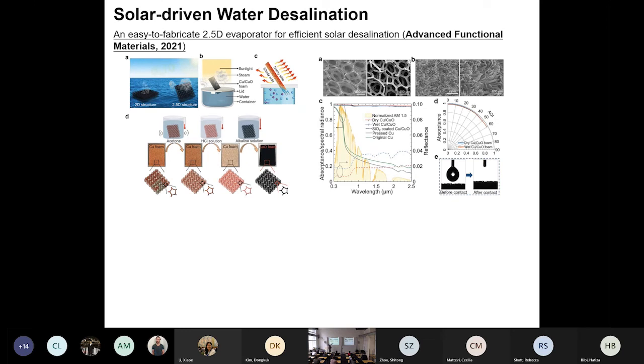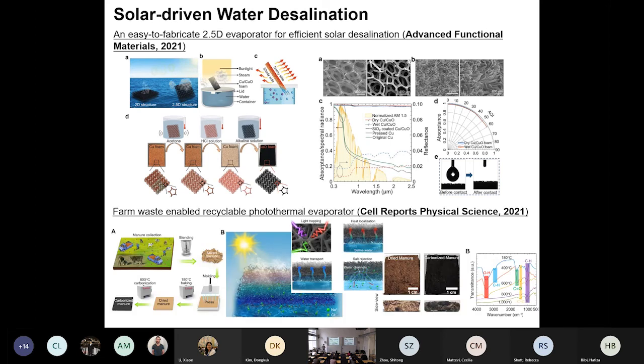Top right corner, you can find the SEM images. On the left in figure A, it's only the copper foam itself. Figure B, this is the oxidized copper foam, the CuO or Cu2O. So you can see there are blade-like structures. Because of the blade-like nanostructures, this material becomes extremely water absorbent. So we achieved a nice evaporation, and then we continued.